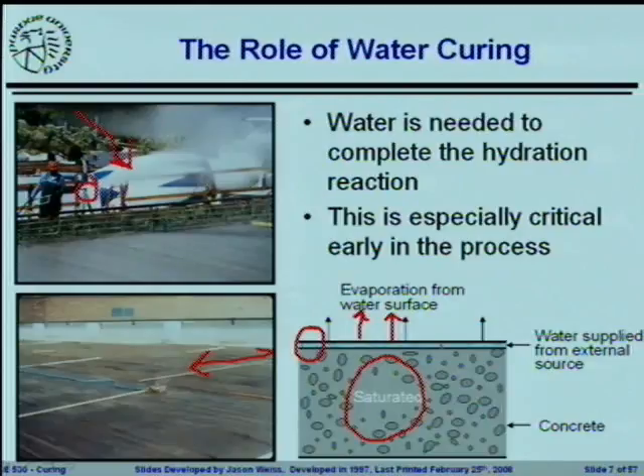The additional benefit is some of this water will actually get sucked into the system. We talked about the fact that when the system sets, when you get that structure formation right around the time of set, the chemical shrinkage is going to continue to increase, but the volume of the system is relatively stable. So it's going to try to reabsorb bleed water. It's going to try to suck water in from the outside edge. If you took a cylinder and placed it into water right around the time of set, you could come back and notice that that cylinder has gained weight. The reason it's gaining weight is it's trying to suck water in from the outside to fill up the empty pores that are being created by chemical shrinkage. So water ponding is the real way where you're going to get water back into the system.